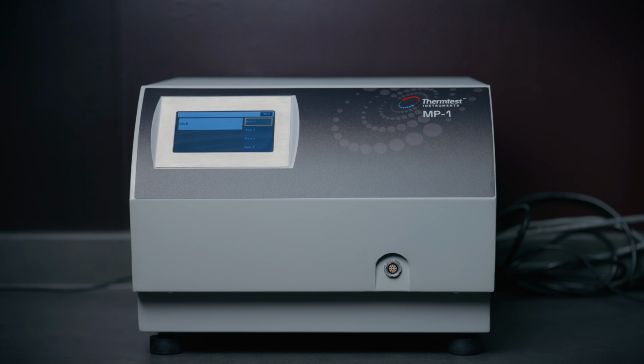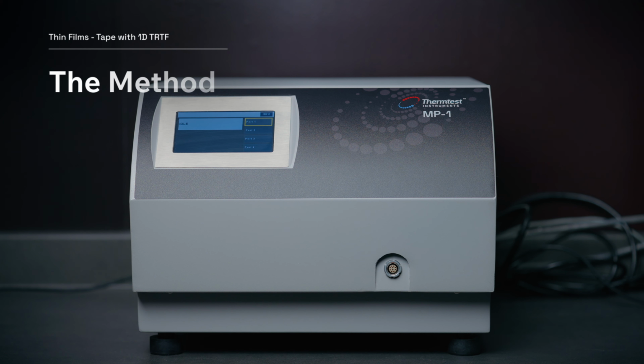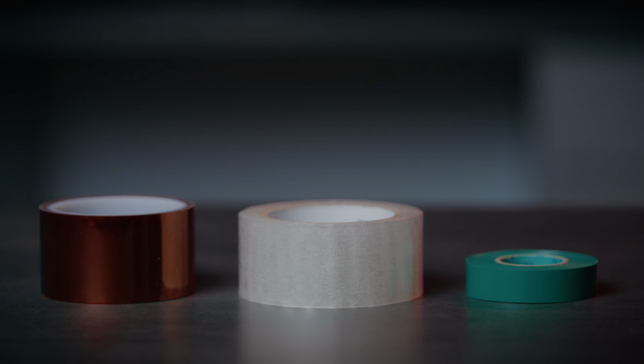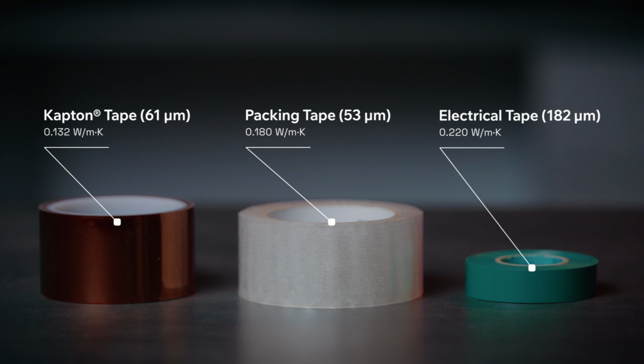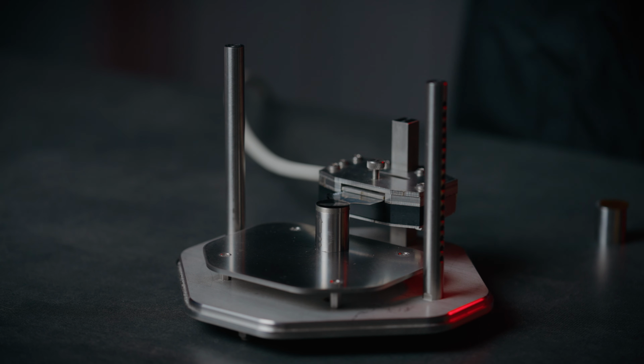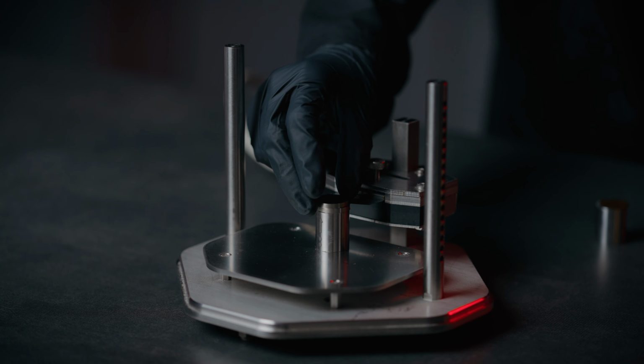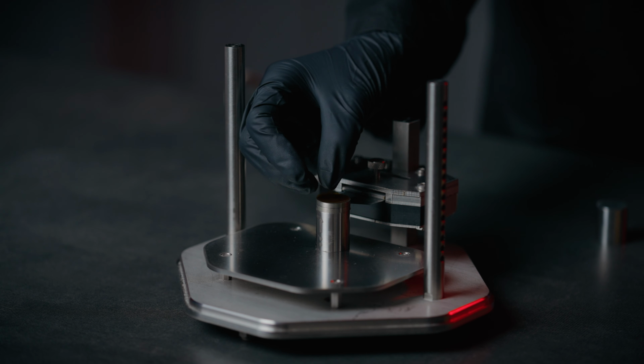To quantify the real thermal resistance of thin adhesive films, Thermtest used the advanced measurement platform MP1 with the patented 1D TRTF thermal resistance thin film module. Three industry-relevant tapes were tested: Kapton tape, packing tape, and electrical tape. Each tape was tested using a layered stacking approach in a controlled steel sample configuration.